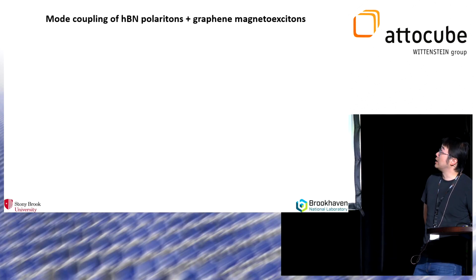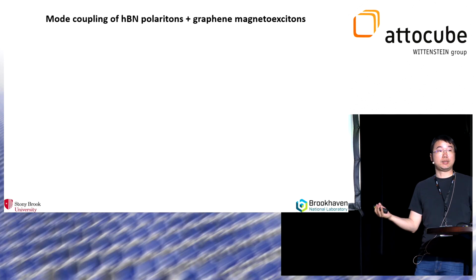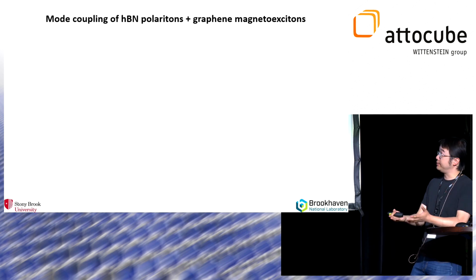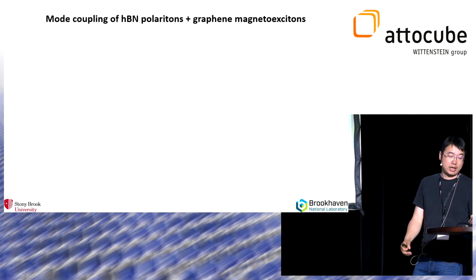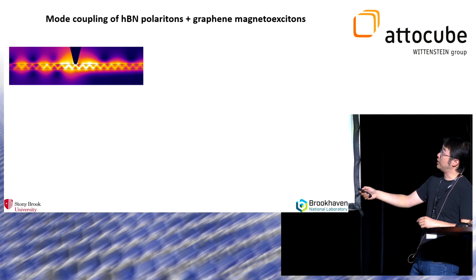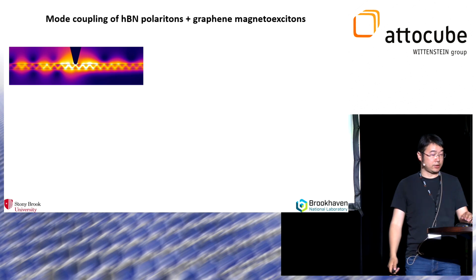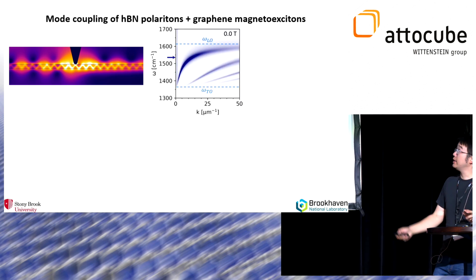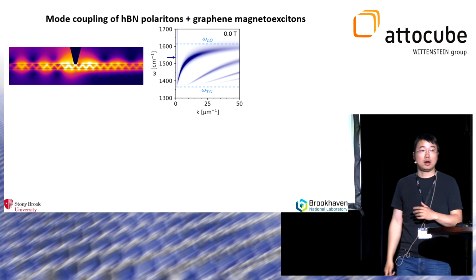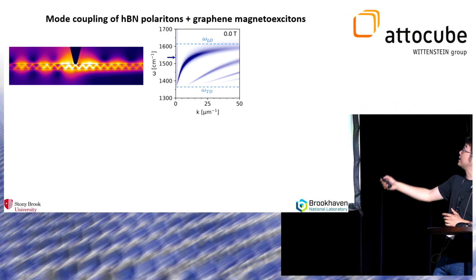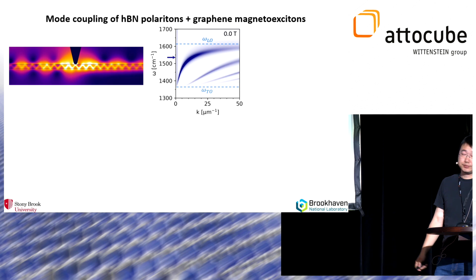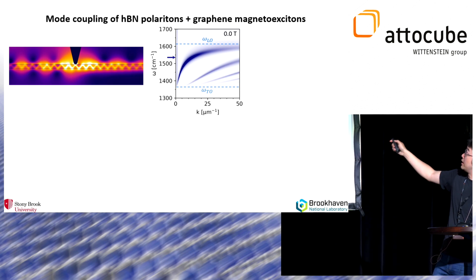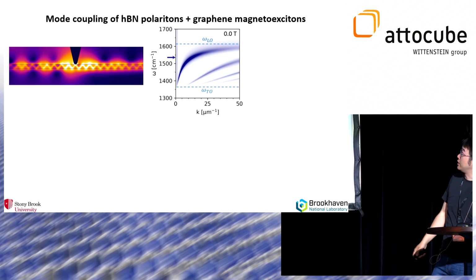So what we do is we put a thicker hBN beneath the graphene, and now we can access polariton modes in the infrared frequency range. This is just a typical dispersion of phonon polaritons in hBN at 0 magnetic field. We have the first branch and higher order branches, of course. We essentially detect only the first branch here. So this is simulation and calculation, right?